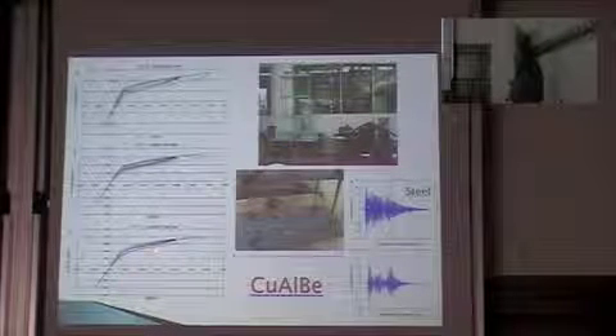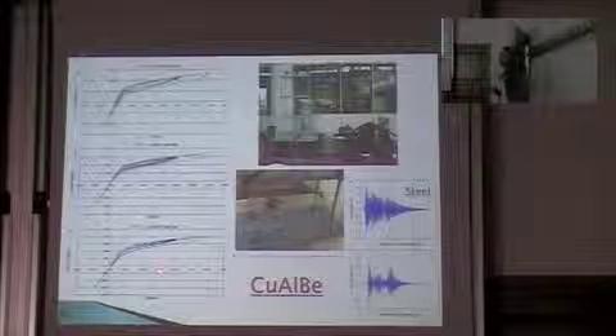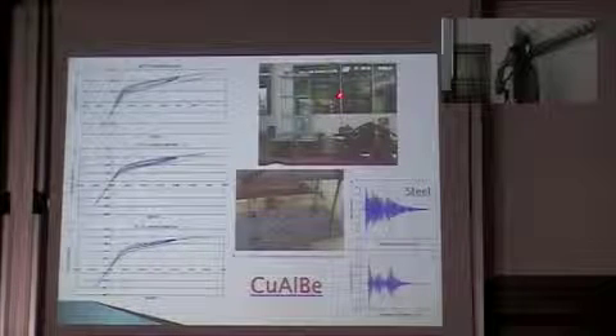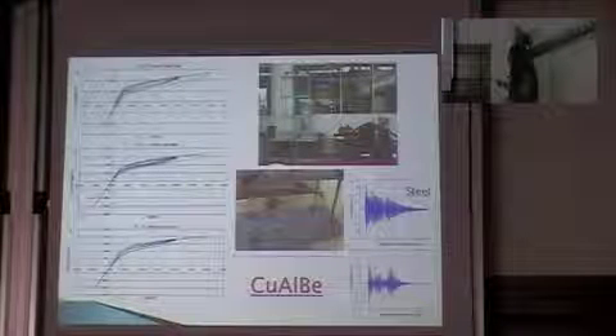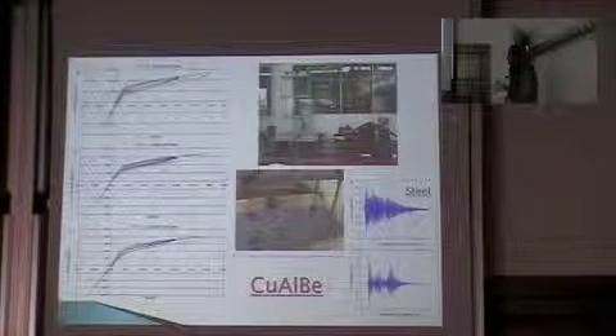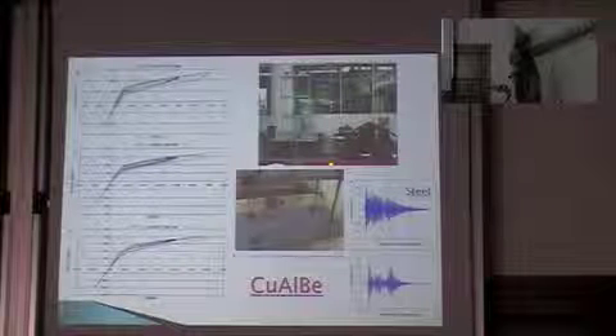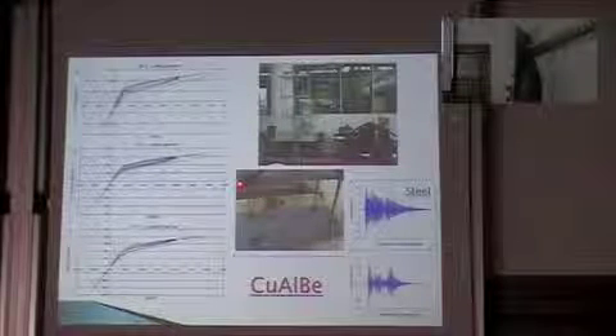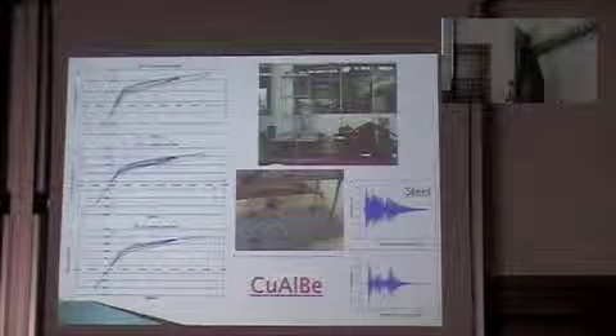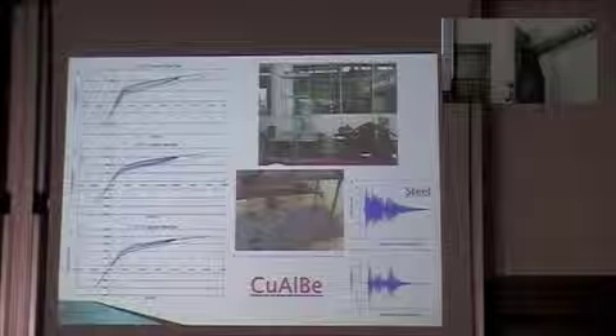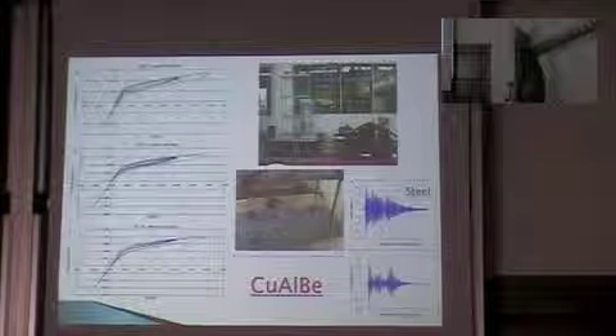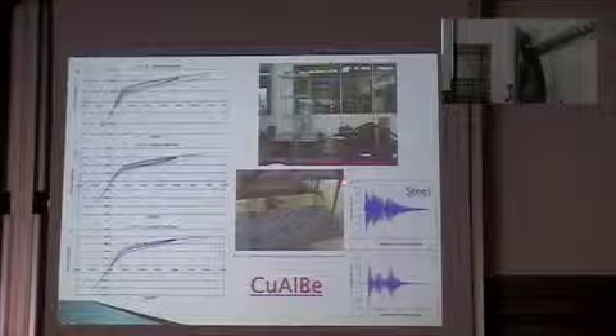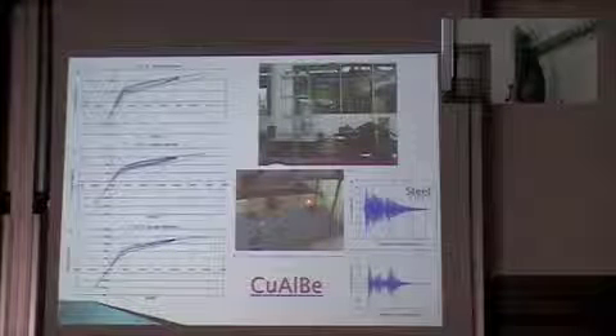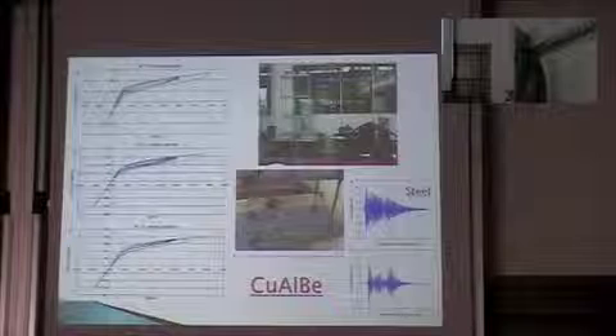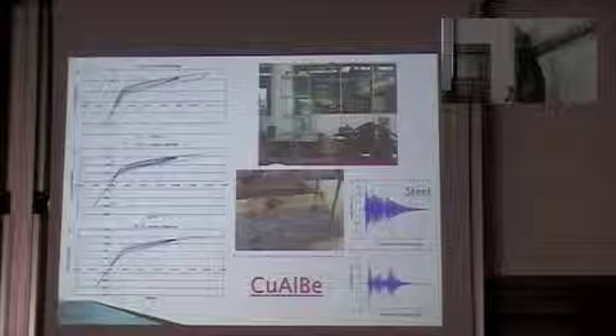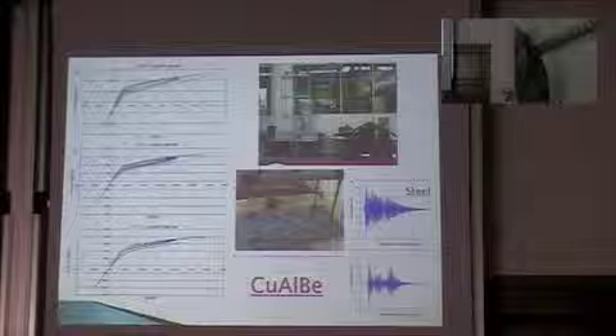Now we move on to the same model structure that we used for our active control test. And we mounted the CuAlBe shape memory alloy braces on the first floor. We compared the response not only without the braces, but also by replacing the shape memory alloy braces with steel ones. Here are the results with steel braces, and here are the results with the shape memory alloy. And you see how we have not only better damping, but also higher reduction capabilities.